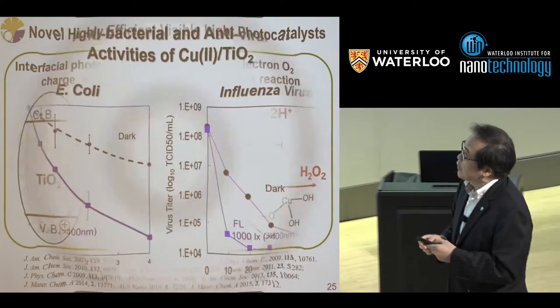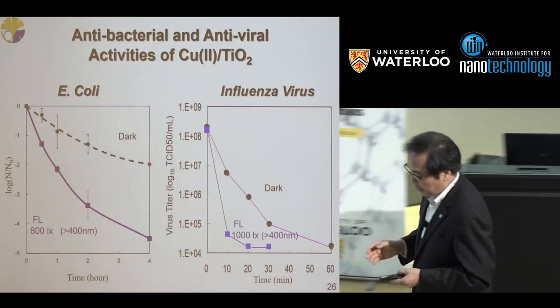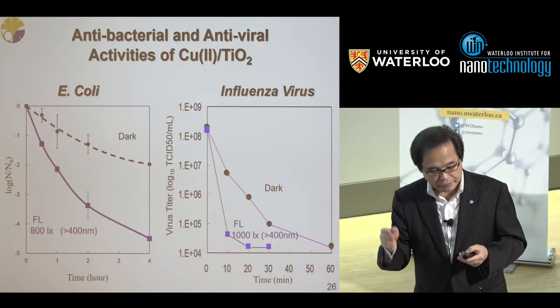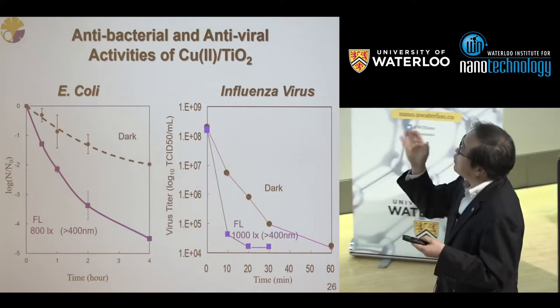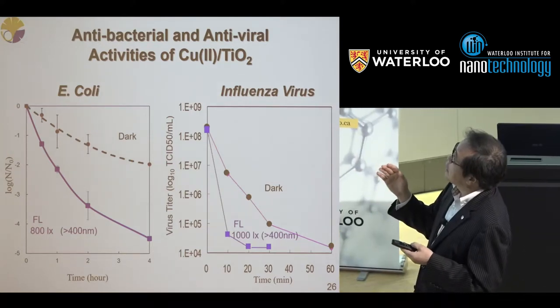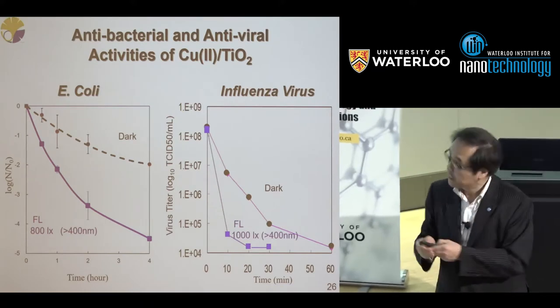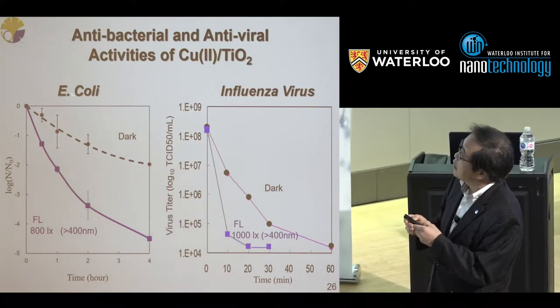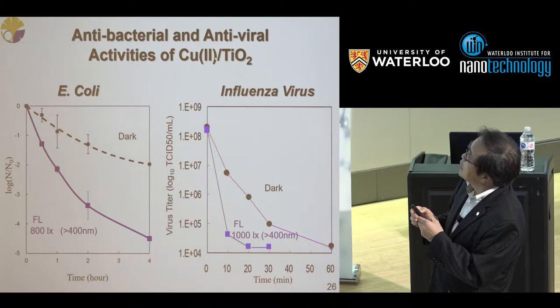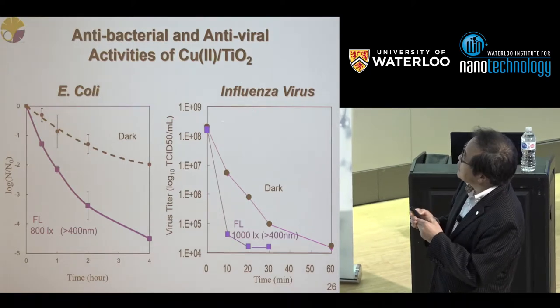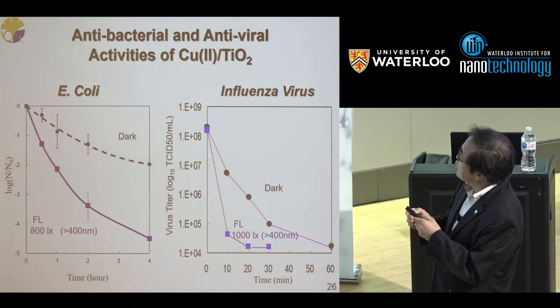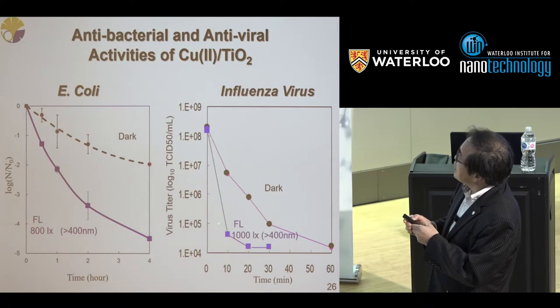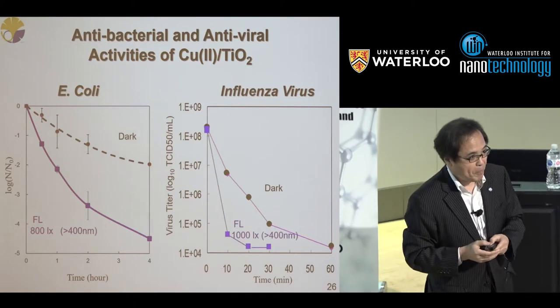And more interestingly, this one, especially divalent copper modified titanium dioxide, has very, very, very strong antibacterial and antiviral activities. This is experimental data, E. coli bacteria. This is the influenza virus case, and activity decreases in the case of virus under the visible light illumination. 10 minutes illumination decreases the activity 5 orders of magnitude.